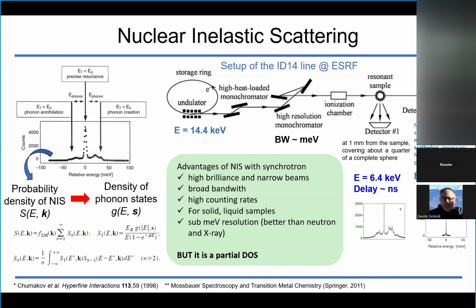At the same time, the nuclear forward scattering, which means the elastic absorption, is also detected, but for technical reasons and for data analysis. So in the end, nuclear inelastic scattering is a fast technique, also precise because we can focus the beam. Moreover, the resolution is under 1 millielectron-volt, comparable or better than the resolution of neutron scattering or X-ray scattering. But we have a limitation.